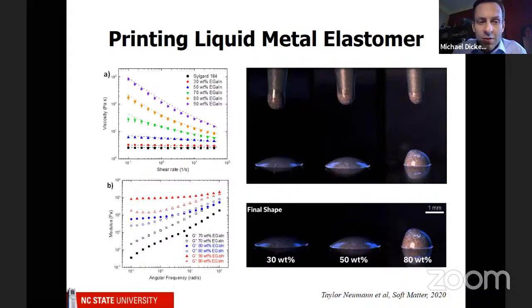Now, if we load it with a lot of liquid metal, 90 weight percent, you can see the viscosity goes up, but when we start pumping it, it goes down by orders of magnitude. So what this means is when you're pumping it, it will flow, but when you stop, it will hold its shape. We also look at the modulus of the material and try to figure out where we can form a gel-like material. Well, without going into a lot of details, the bottom line is that it works. And the video is not playing.